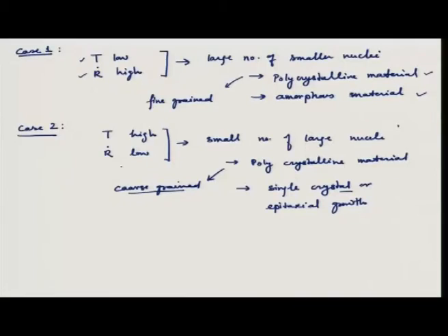energy. If we give high temperature, and since the deposition rate is also slow, the number of atoms which are coming to the surface is very small per unit time. So, each atom or molecule finds a suitable position, and the suitable position is where it forms a single crystal, or if it can prefer, it will form an epitaxial deposition if my substrate is also crystalline. And the crystal structures of the substrate and the thin film are matched easily.